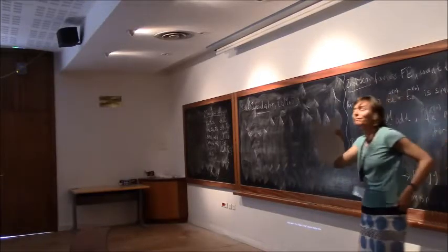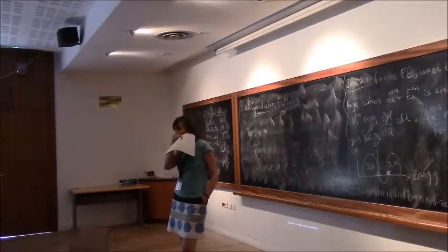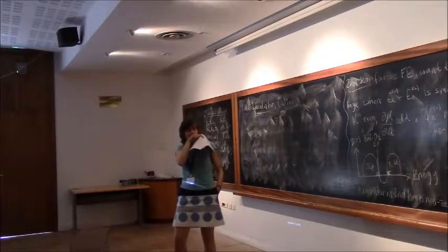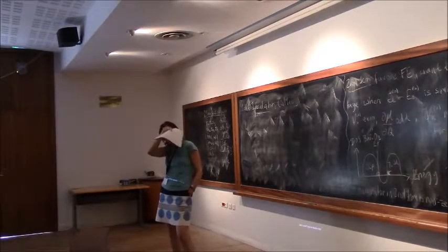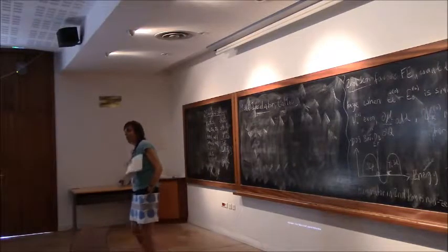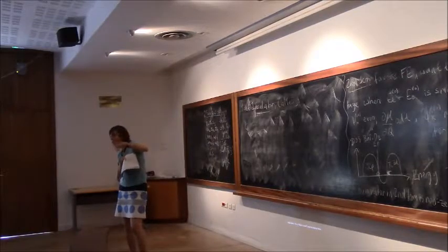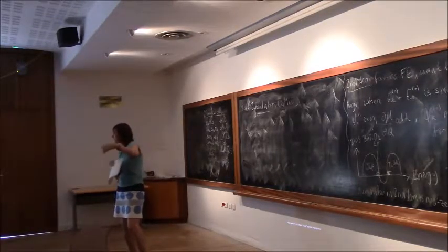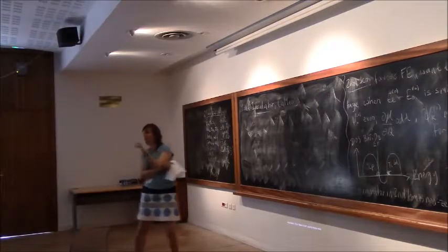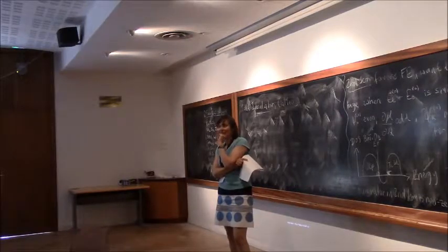Okay, very good question. Is it possible to disturb the balance of strontium titanate by integrating it with a very highly metallic system like graphene or 2D materials? I'm not sure about graphene. But when you strain strontium titanate, for example, it does become ferroelectric. When you dope it with a little bit of calcium, it also becomes ferroelectric. That's very interesting. I think it's not understood. It's believed maybe the calcium's so small it rattles a bit and drags everything else along with it. But it's so close to the boundary that anything you do to strontium titanate can make it ferroelectric.